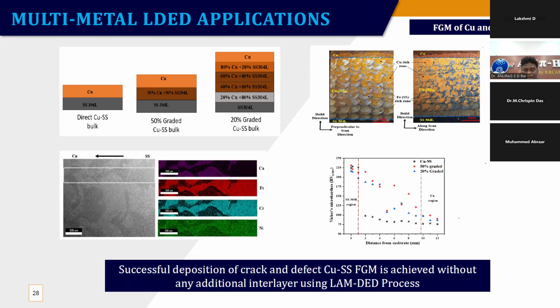So what we are trying to do with the FGM is, in spite of having a step change in the composition, we are going to have a graded composition change. For example, you see on the 20% graded copper SS bulk, we have 100% SS at the bottom. Then we are increasing 20% copper on that and 80% SS. Likewise, if you go to the upper, the top layer, you have 100% copper available. So this made a very smooth transition of copper to SS, and at the interface now we have the change in the thermophysical property in a graded way, and this is definitely making a lot of difference in terms of the components that can be built using this technology, which is not possible otherwise.